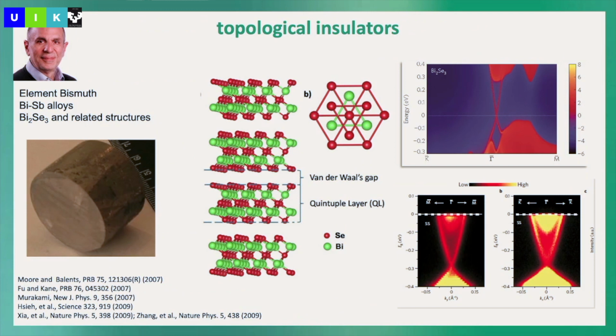Anyway, but the first idea then was, if you start with bismuth, you alloy it with antimony, and then also, I would say this was really the idea of Bob, to go to a famous thermoelectric material, which exactly was this first and still one of the best topological insulators. And for me, it's always amazing that the theory is so fantastic. So you do a calculation with the surface, calculate the properties of the material, including the surface, you make a slab calculation, and you really see whether there's a surface state or not. Okay, so this was amazing.